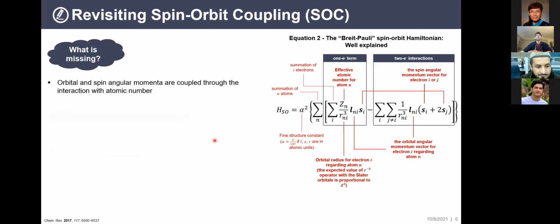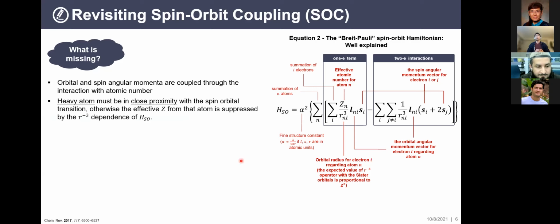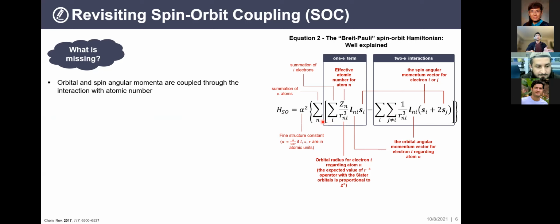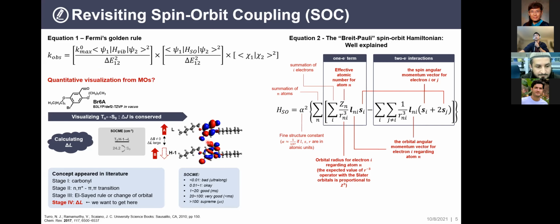So what is missing here is, importantly, for our interest, we are very interested in a certain way to combine the heavy atom effect together with the orbital angular momentum change business. So we hypothesized that, by the form of this equation, it's very important that your heavy atom, let's say bromine, needs to be in close proximity to the orbital angular momentum change. So for instance, in the orbital I showed before, if bromine is contributing to the in-plane to out-of-plane change, then you're using a heavy atom to directly induce orbital angular momentum change. And wouldn't that lead to a very large spin-orbit coupling value?